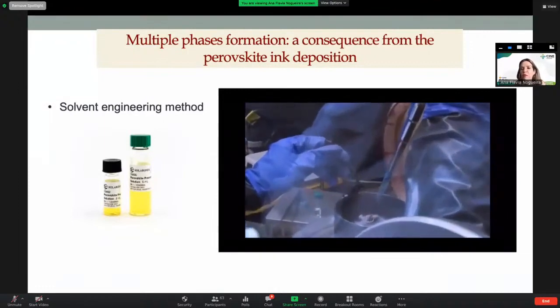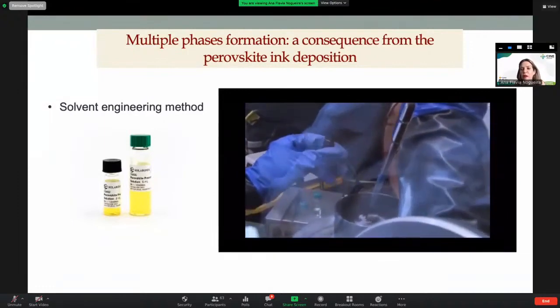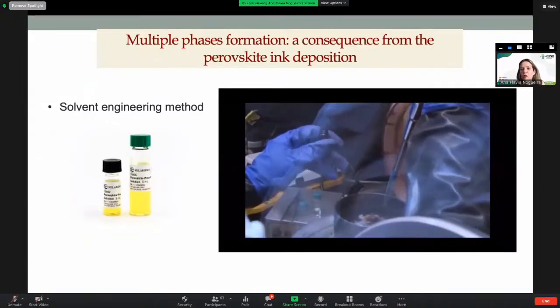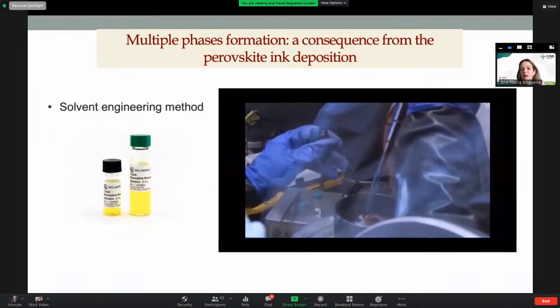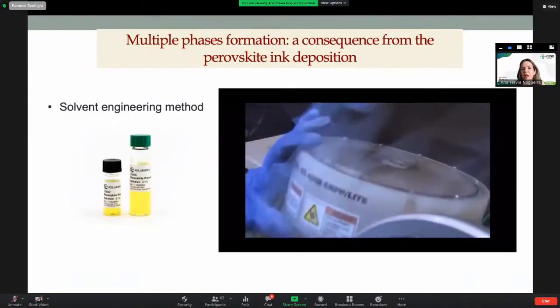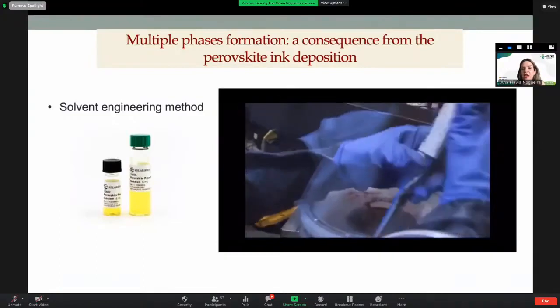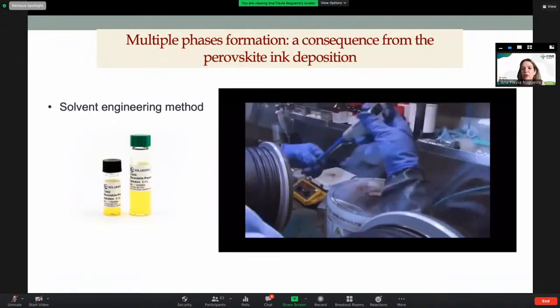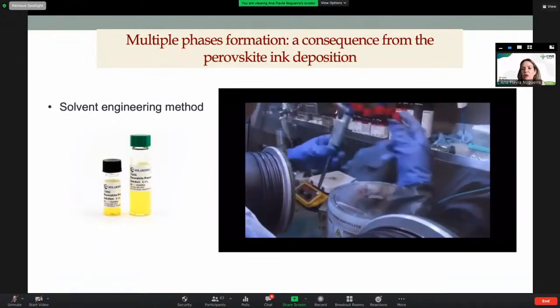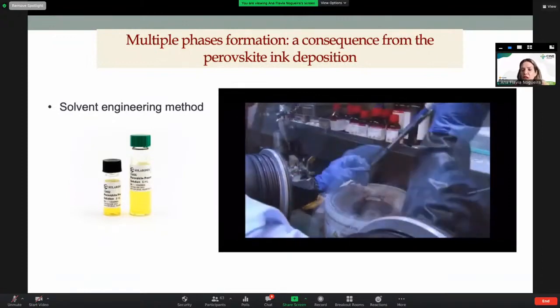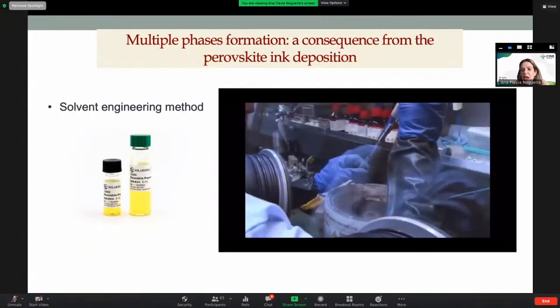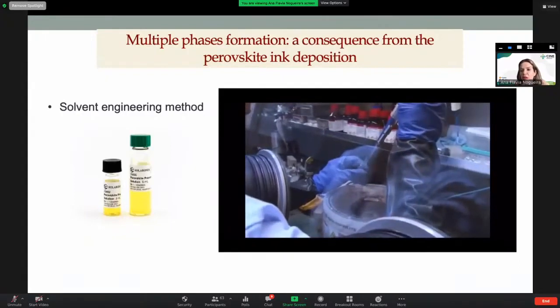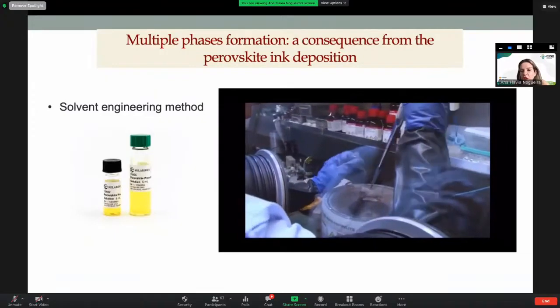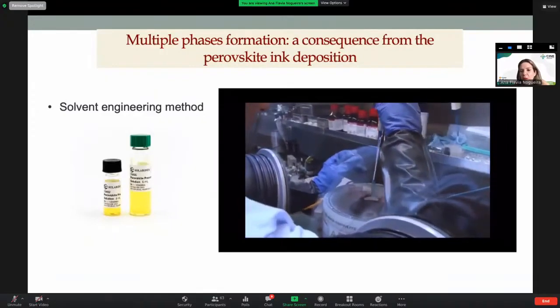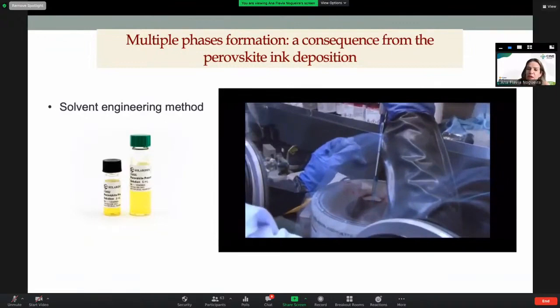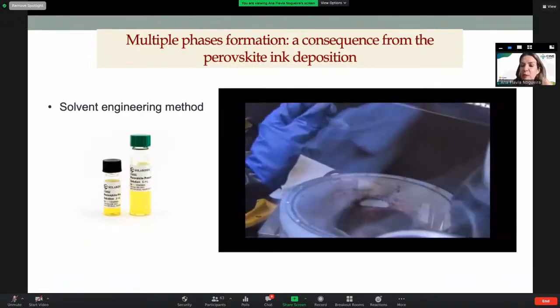So this is my postdoc. She's spreading the solution on top of the tin oxide layer. I just want you to pay attention that she's going to drop the solvent. As soon as she drops the solvent, which is chlorobenzene, you're going to see a change in the color of the film. Just at this moment, when she's dropping the solvent, you can see a change in the color of the film. Okay, so now you are forcing the formation of the perovskite.